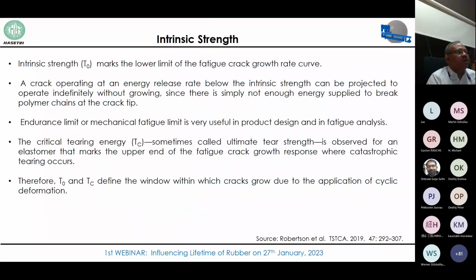So intrinsic strength marks the lower limit of the fatigue crack growth rate curve, and below this, the crack will take infinite time to propagate further. So that can be seen as the endurance limit, and this is very important while you design a product like a tire or any rubber product. If you know that this is the threshold limit and your operating condition is below this, then you will be very safe.